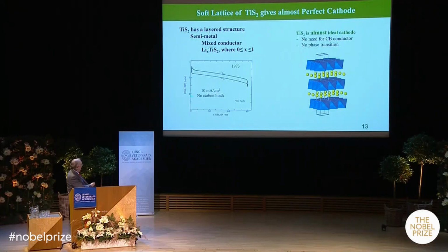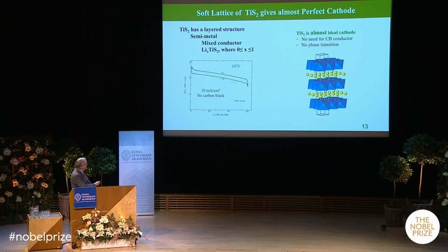Okay. And the other key thing I point out, because this is a good conductor, we got current densities of 10 milliamps per square centimeter. Typically, today it's about 1. Okay. So this was an ideal cathode, except for one thing. The voltage was a bit too low. And so we didn't need any carbon black in there, and there's no phase transition. So this is a single phase all the way.